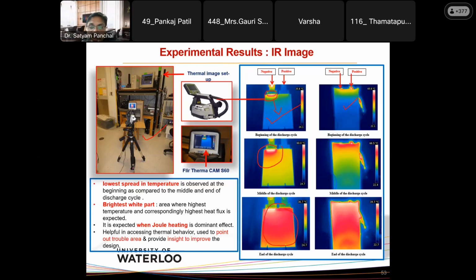Second, the brightest white part in all images is where the highest temperature and corresponding highest heat flux in watt per meter square is expected. And third, it is expected because Joule heating, that is I squared R, is the dominating effect, and that is why you can see this higher one here.